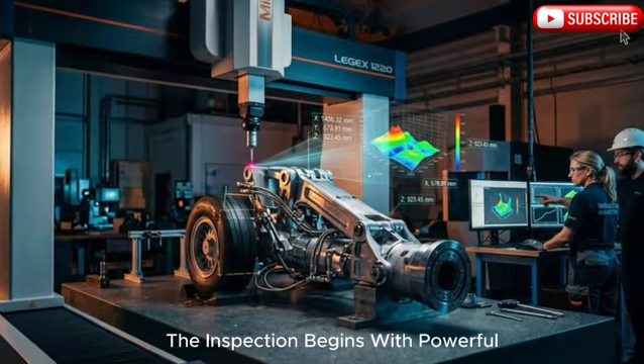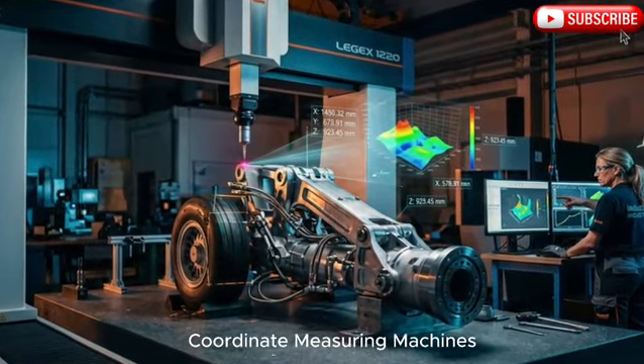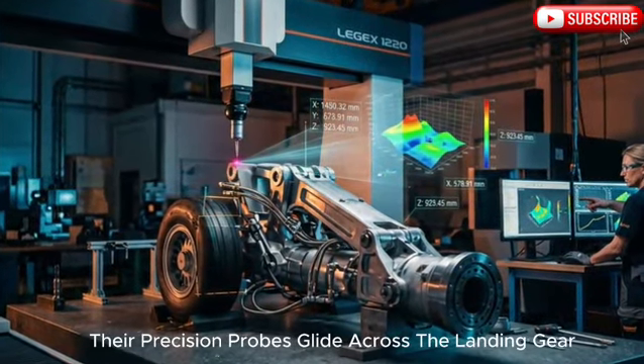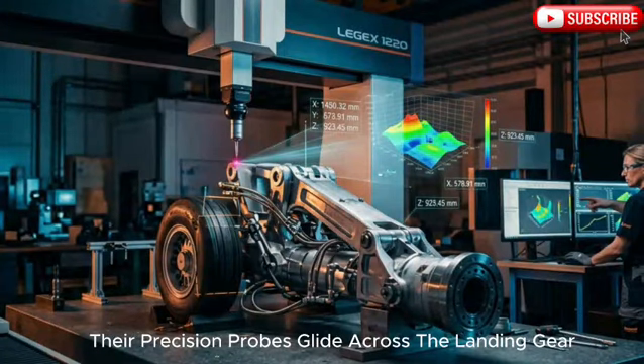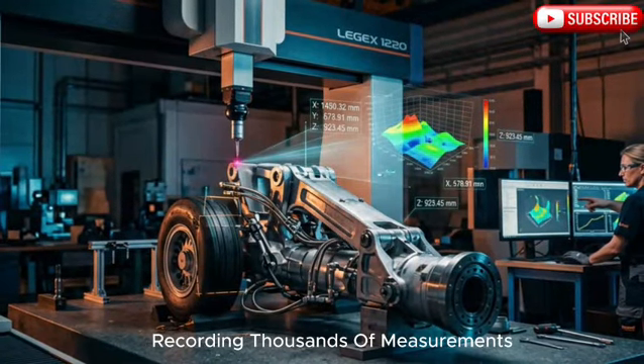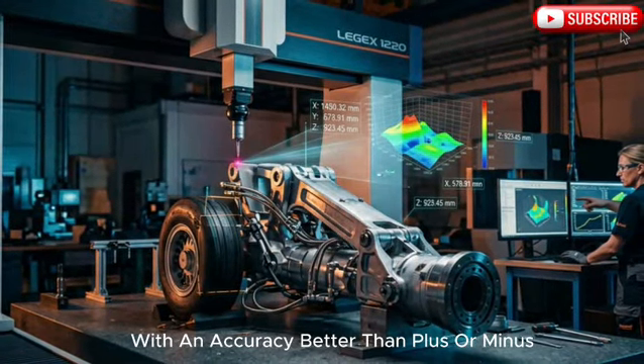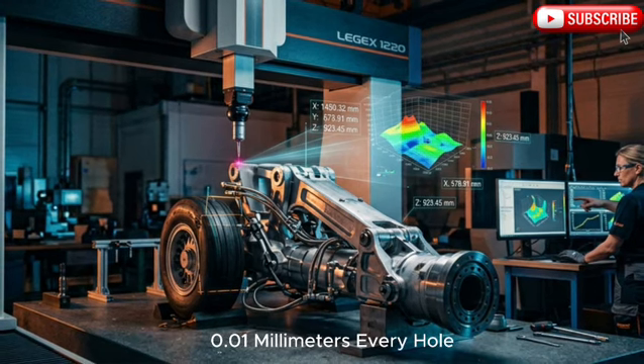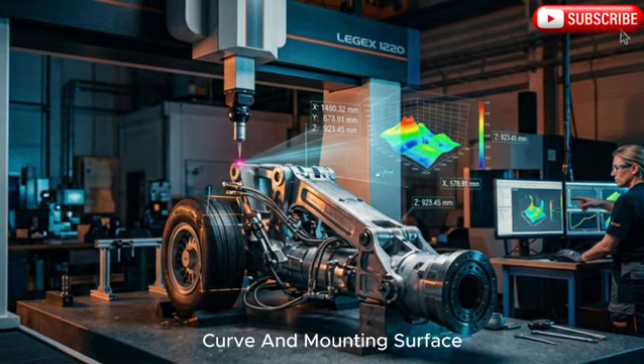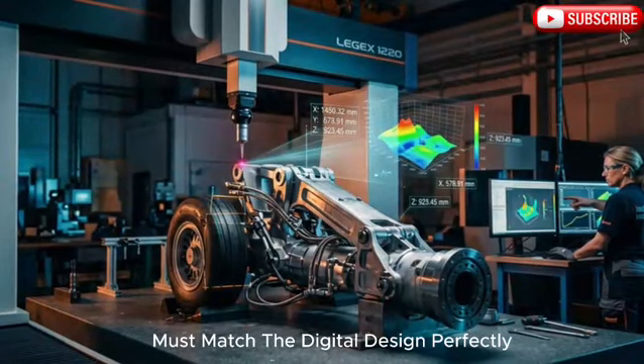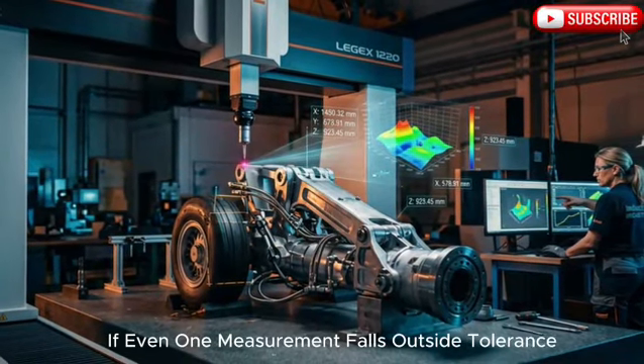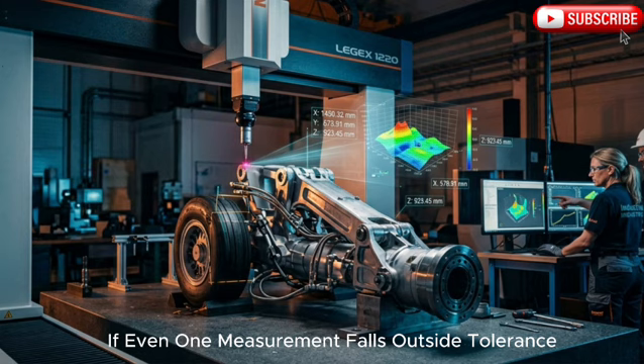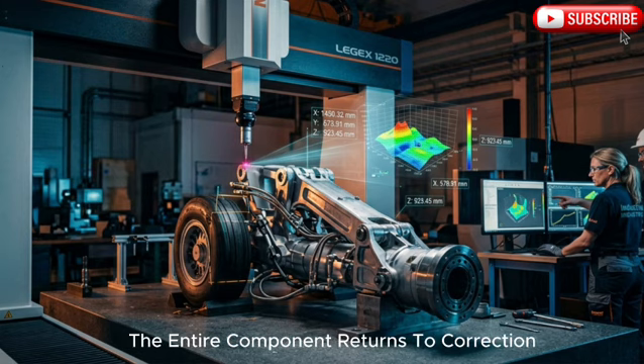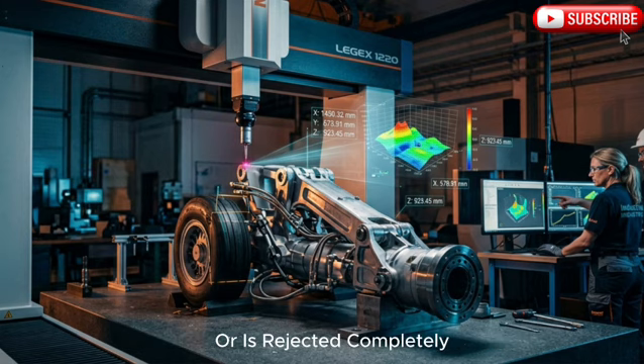The inspection begins with powerful coordinate measuring machines, or CMMs. Their precision probes glide across the landing gear, recording thousands of measurements with an accuracy better than plus or minus 0.01 millimeters. Every hole, curve, and mounting surface must match the digital design perfectly. If even one measurement falls outside tolerance, the entire component returns for correction or is rejected completely.